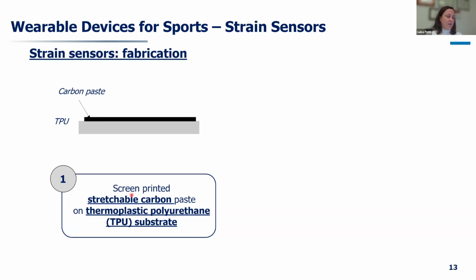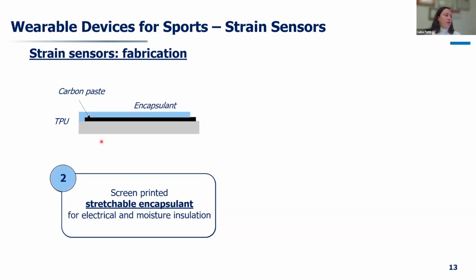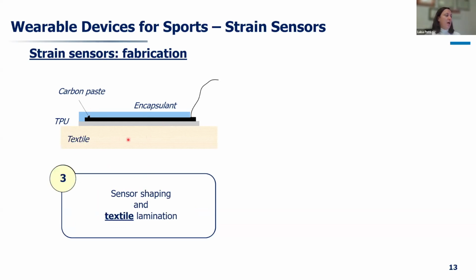So a very nice technique for mass printing, also when used on a larger scale, of a stretchable carbon paste on a thermoplastic polyurethane substrate. Moving on, the stretchable encapsulant, so everything again screen printed, and then shaping the sensor and laminating it. This is laminated with heat lamination, basically ironing, similar to ironing on a textile. And the textiles are from the textile company that I mentioned. So textiles used for the t-shirts of the athletes.